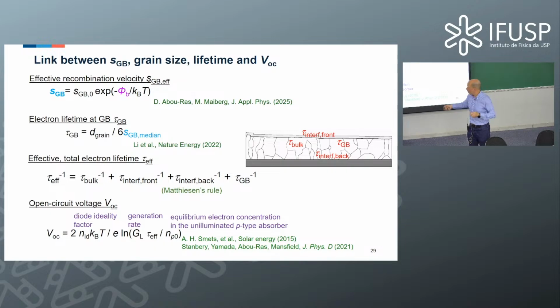boundary recombination on the VOC is, or to calculate the losses, what we can do is to look at the situation with and without grain boundaries, and then we can see that basically for this term here, we can just put in this magnitude or this equation, right? And if we look at differences, basically the ln of differences, or the ln of a term minus the ln is basically nothing else than the ln of term 1 divided by term 2. And this actually gets rid of the GL and this electron concentration, and we only have lifetimes.